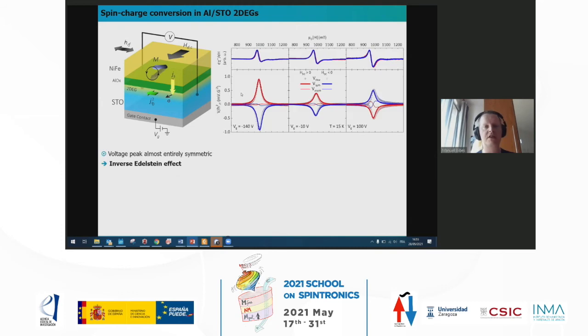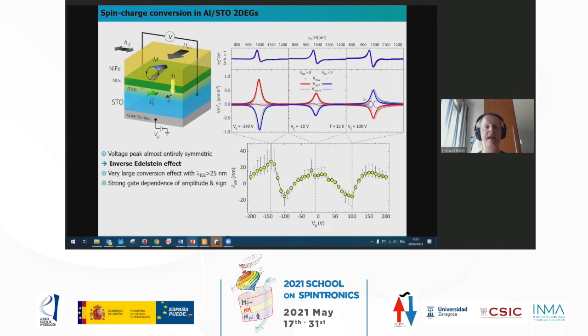So we do the same kind of experiment, and we also see a strong spin to charge conversion signal, also changing sign. And here we have something even more complicated with several changes of sign. And our understanding is that the LAO STO results correspond to this range here.